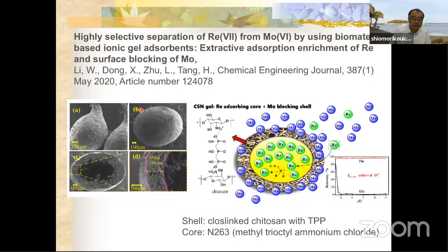But some researchers reported some results. Professor Lee reported the selectivity of a core-shell layer in the separation of rhenium and molybdenum. Like this, Mo was removed at the shell layer, and only rhenium can pass through the shell layer into the extractant core. Selective separation was achieved successfully.